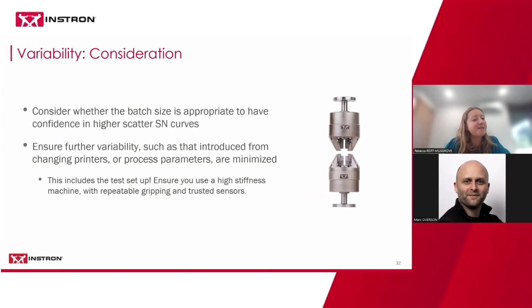And we also need to make sure we don't introduce further variability. That might be introduced from changing printers or processing parameters. We need to make sure we minimize that variability. But this also includes the test setup. So ensuring that you use a high stiffness machine, repeatable gripping, things like pneumatic grips, trusted sensors, so that when we get scatter in the data, we know that it's from the material itself and not from the machine or the test setup.